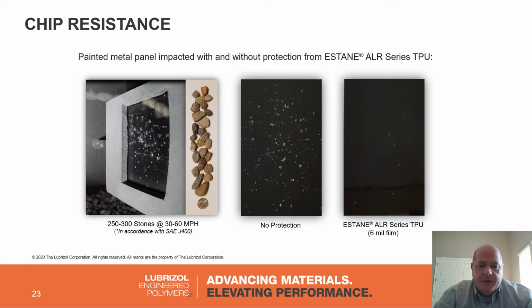And another test that we did with this film on this black plastic is a stone impact test, where basically you're taking a set of stones defined by an SAE standard and you're shooting them at a plaque at 30 to 60 miles an hour. And this is looking to simulate stone and gravel on the roadways. If you look at the plaque on the left, that had no protection, no TPU over the top of it. It gets pretty chipped up, as you might expect from stones at 50 miles an hour. If you look to the right, the TPU gives a very high level of protection from that chipping, as there's only a few on that particular plaque. So again, the TPU is giving impact resistance along with abrasion, UV resistance, chemical resistance, and all the other nice things that TPU can do for the underlying plastic.